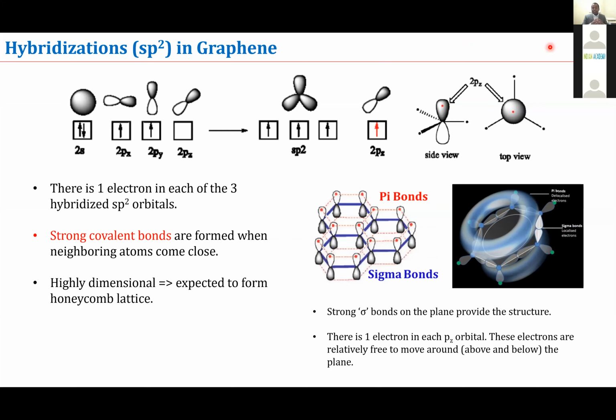If you compare with silicon, which is about 1400 centimeters square per volt second, this is really high for a material just one atom thick. So you can see here this is the cartoon where you have the sp2 hybridization that contributes to the strength of graphene, and you have the pi electron that contributes to the pi cloud, and hence to the electrical conductivity.